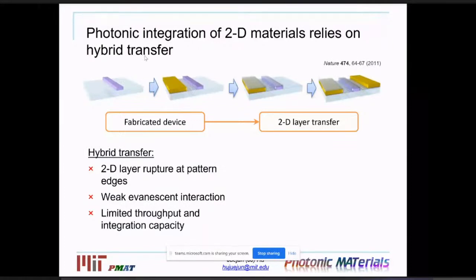So in a hybrid transfer process, you start out by fabricating these photonic structures, photonic circuits. Then on top of that, you transfer these 2D crystals onto the photonic structures. Now, the challenge with this kind of hybrid process is, one, because the substrate now contains this rugged morphology. Okay, so when you're trying to transfer this atomically thin crystal onto this kind of structure, you tend to rupture at the edges of the topology, and this will compromise the yield of such a process.